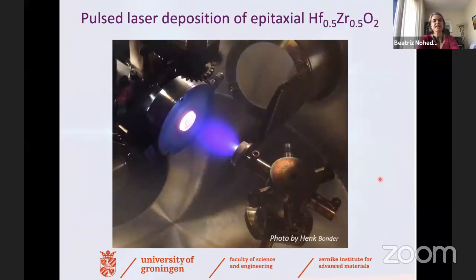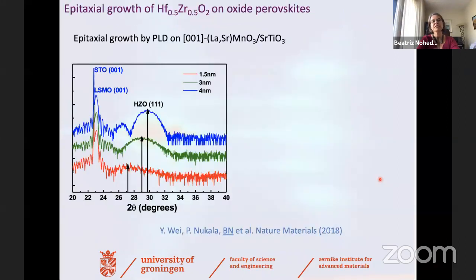We also did that. We grew hafnia or hafnium zirconium oxide by pulsed laser deposition on a completely different type of substrate, on perovskite substrate, and with a buffer layer or electrode of lanthanum strontium manganite, trying to make devices with these materials. And we found several surprises.